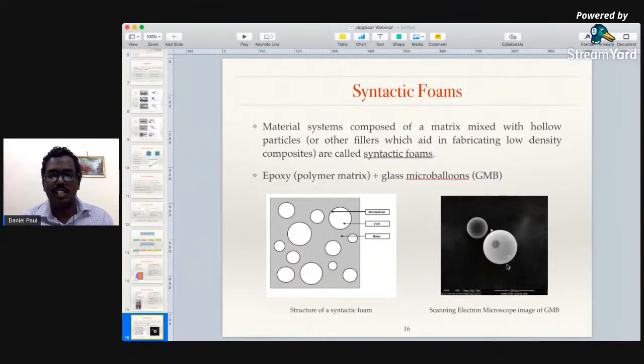On the right side, we can see the scanning electron microscope image of the hollow particle that we have used, which are glass microballoons. The matrix that we have used is a polymer matrix called epoxy, which is a commercially available polymer matrix, and we have used glass microballoons to act as the hollow particles to create these syntactic foams and to study them in impact resistant structures.